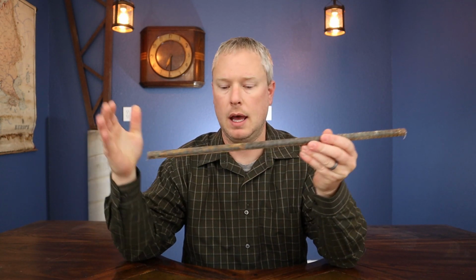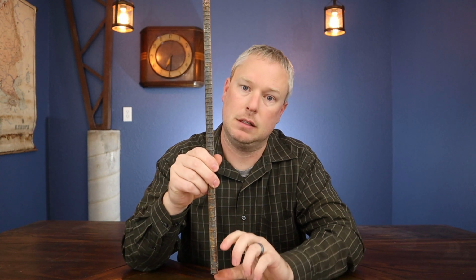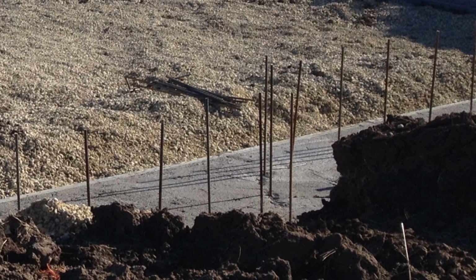Now let's move on to rebar, and that is a very important thing that we need to talk about. I use number 4 bars throughout all of my walls as well as my footings. My footings themselves actually had number 5 rebars, but I used a number 4 rebar just like this. I cut it at 36-inch lengths and then bend it 90 degrees at the 8-inch mark. So that meant that I could stab the short end into my footing before it had time to cure and have at least 24 inches of it sticking up out of that footing that then would be engaged by the vertical rebar that is in the ICF blocks.